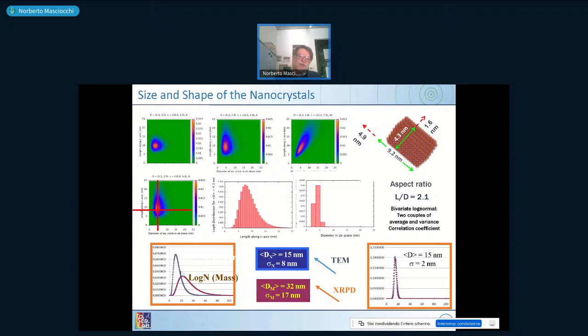And one thing I want to show is that the log-normal function can be used in two different ways. The one in number and the one in mass. The log-normal in mass means that you just assume that you have measured data by scattering techniques, and you may get information such as distribution. You can see them here in red. If you use the same material and you go to a transmission electron microscope and count the size of a different sample, you end up with a different distribution.